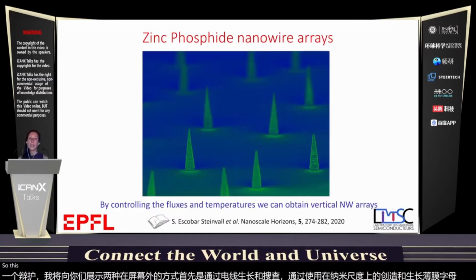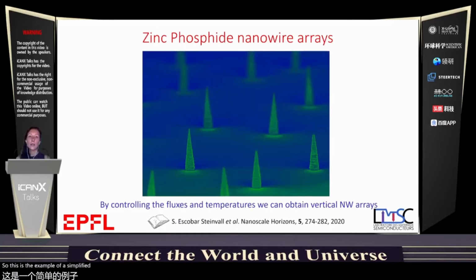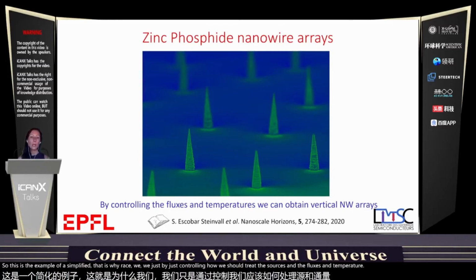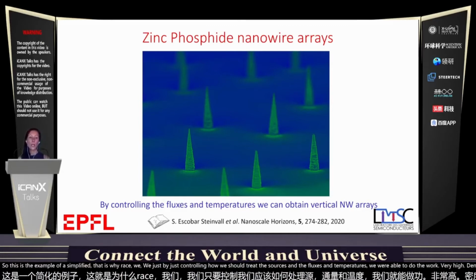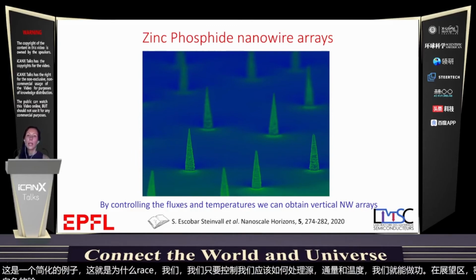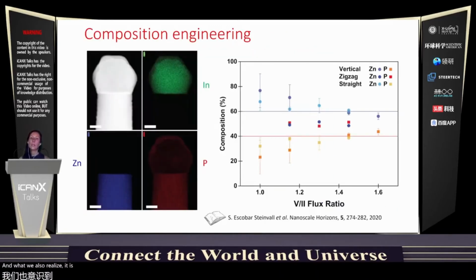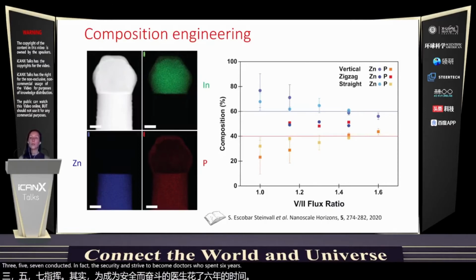So this is the example of zinc phosphide nanowire arrays. By just controlling how we treat the surface and the fluxes and temperatures, we were able to grow a very high density of zinc phosphide nanowire arrays, as you can see here. And what we also realized is this compound is quite different from III-V semiconductors. In fact, the stoichiometry in III-V semiconductors is very fixed. For every element III, you have an element V.